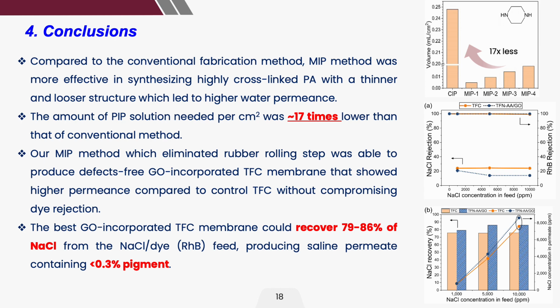In the conclusion, I would like to highlight that the MIP technique that was proposed here could actually produce the TFN membrane, but using much less chemicals to form the polyamide layer. In our case, we realized that it actually needs less than 17 times the chemicals to produce the polyamide layer. And using the MIP technique, we also found that we can produce a membrane that has the potential to recover 79 to 86% of the NaCl from the feed solution, and by achieving a good quality of saline permeate containing less than 0.3% of the pigments.